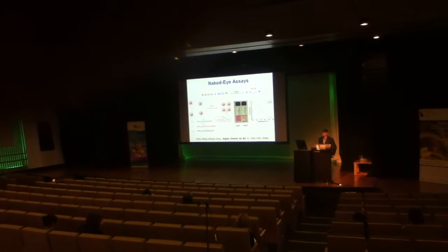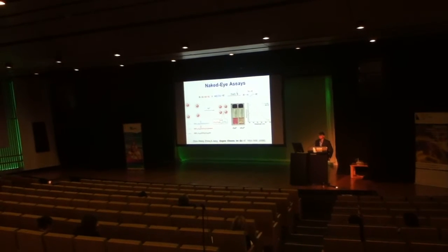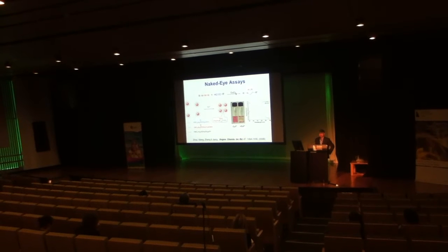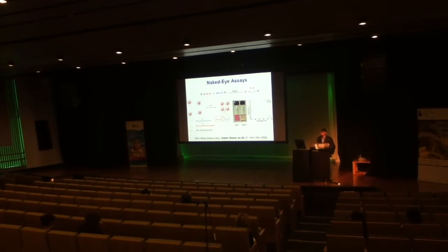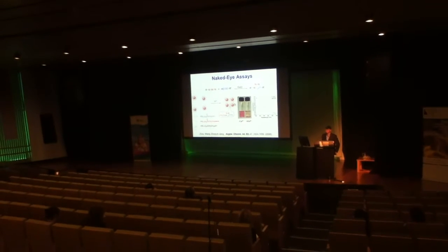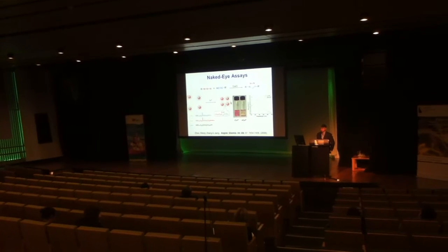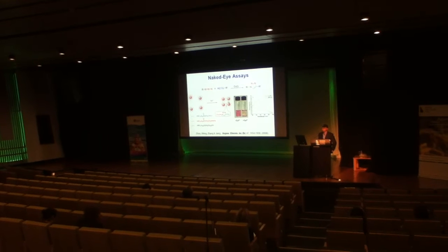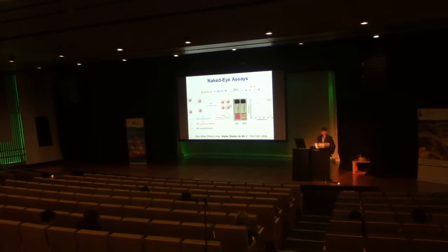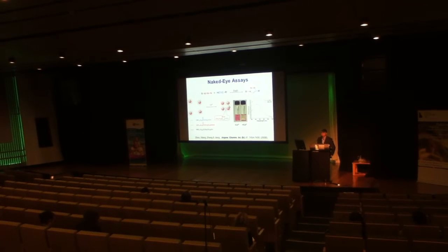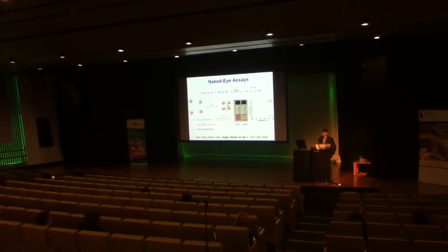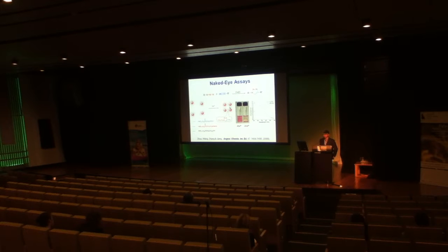And this reaction is extremely selective because only copper catalyzes this reaction. We can put high concentrations of mixtures of other types of ion in, and they would all look like that. Also, in terms of a detection limit with naked eye, we could go to sub-micromolar. So that's, I think, already a record for detection of copper without using advanced instruments.